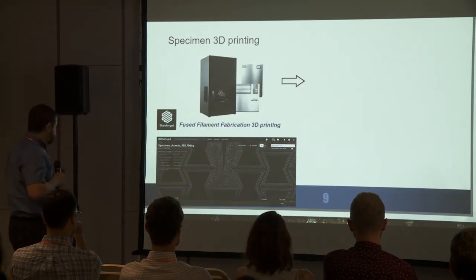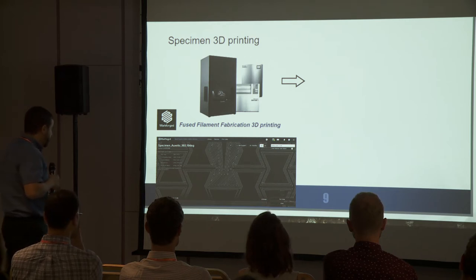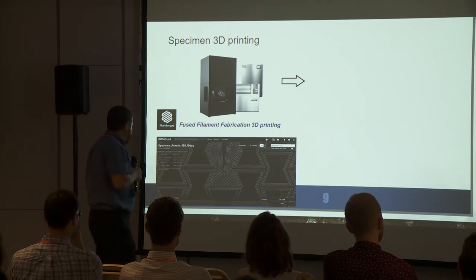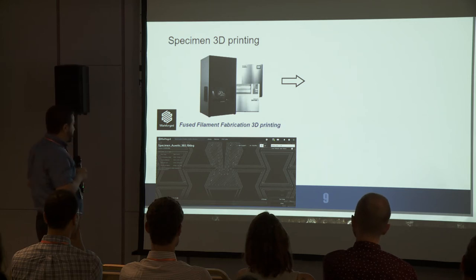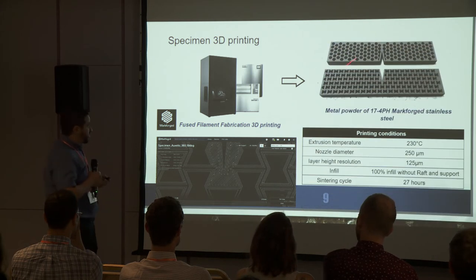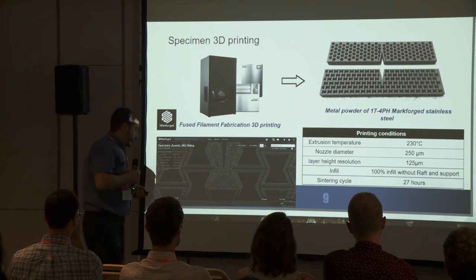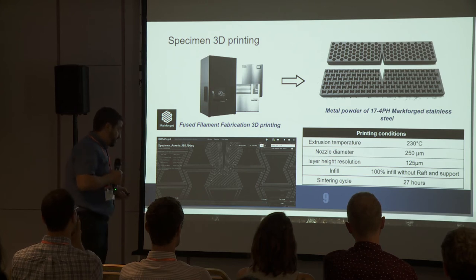After that, the specimens were printed by a Markforged machine, a 3D printer using the fused filament fabrication technology, and these are the results. The extrusion temperature was 230 degrees, and the nozzle diameter was 250 micrometers.